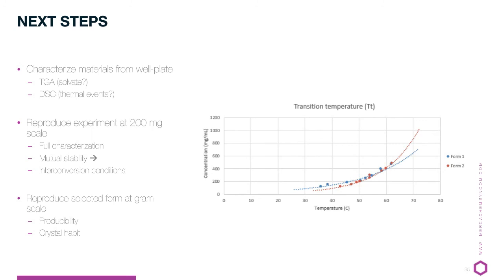In the graph, you see the form 1 and the form 2 from this example, where the form 2 shows to be less soluble and therefore more stable at low temperatures. Your form 1 is more stable at higher temperatures. Transition temperature is around 55 degrees.